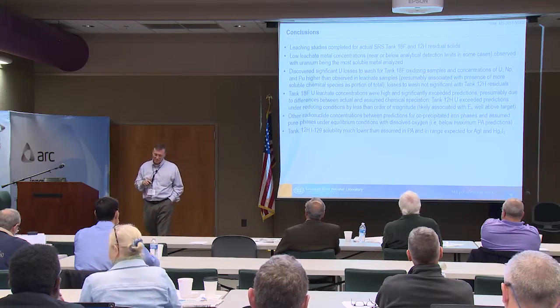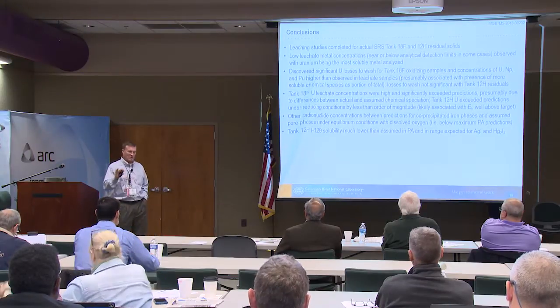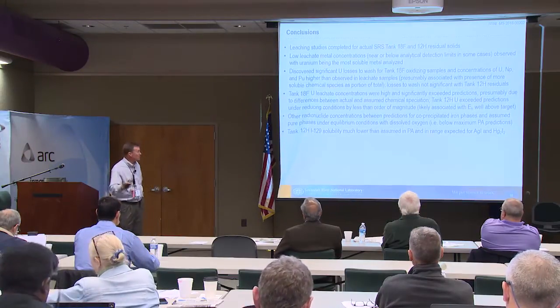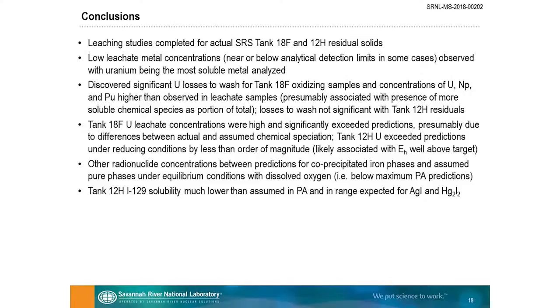Conclusion. So I didn't really go through a detailed comparison of what we saw versus the predictions. But in general, Tank 18 uranium leachate concentrations were high and significantly exceeded predictions. Uranium was more soluble, as I mentioned, for tank 18 because of that phase change and reaction with CO2. So uranium for tank 18 and in one case for tank 12 as well exceeded predictions.